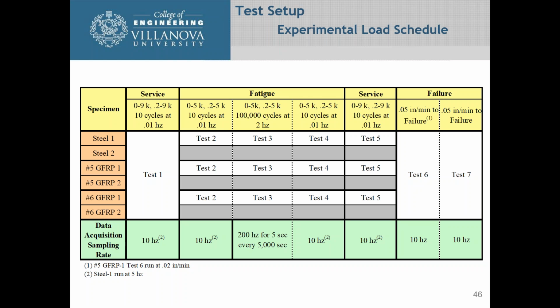Test 1 and test 5 are a comparison to see what happens after 100,000 cycles of loading. Has there been a reduction in strength? And test 1 and test 5 give us that information. And then the last thing we did with test 6 and 7 were we wanted to fail the section.